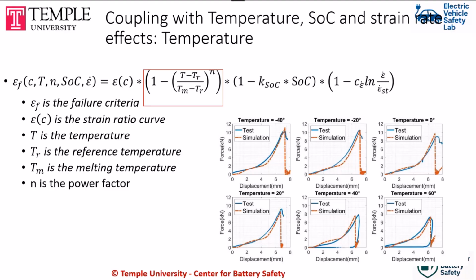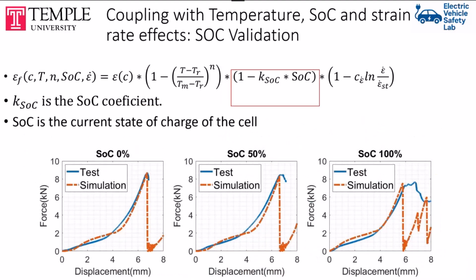Then this is the validation for temperature dependency. This is the validation for state of charge. State of charge is less of a big deal. The range of the values is from a little bit less than 8 kilonewton to more than 8 kilonewton. So the extent of that is less than the temperature dependence, but still there is a variation. Again, we have papers to show how to model the SOC effect itself, but now we have added that also to the failure prediction.